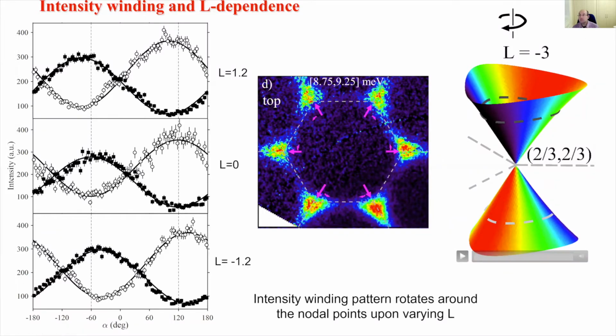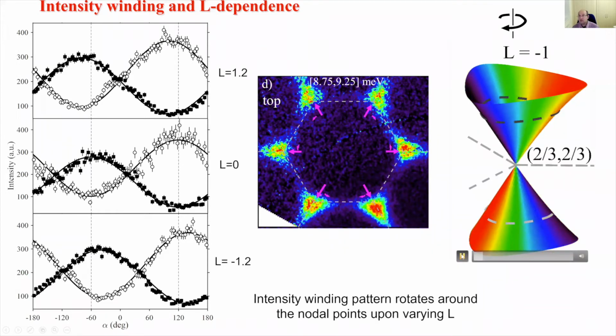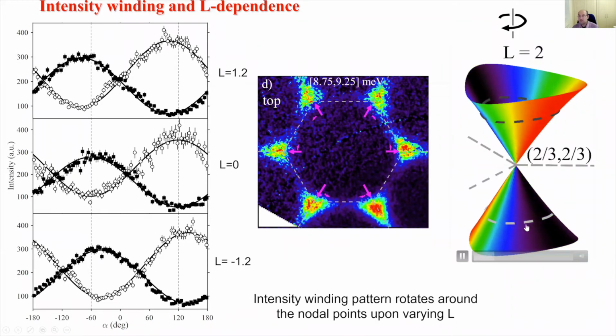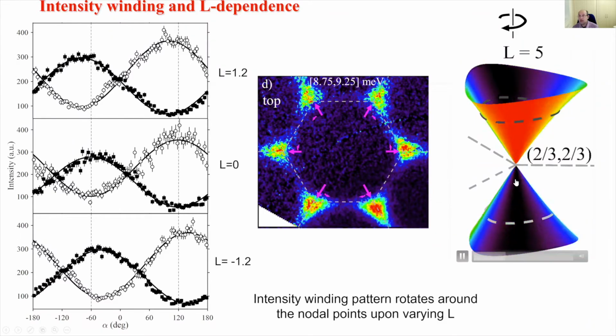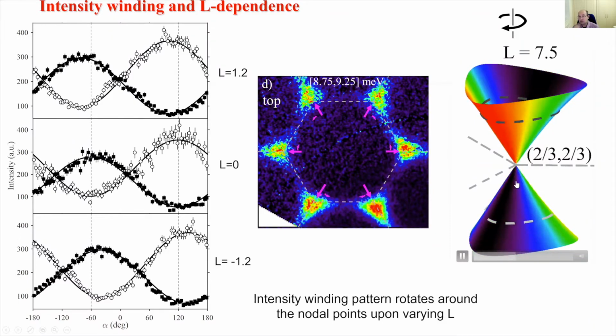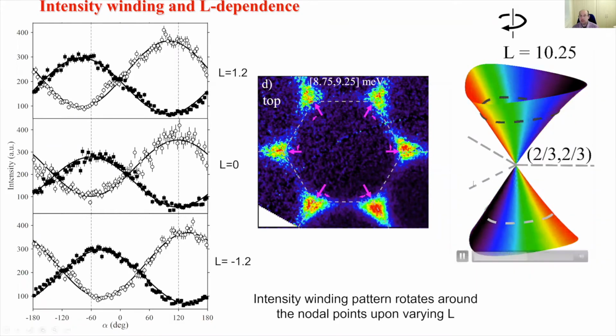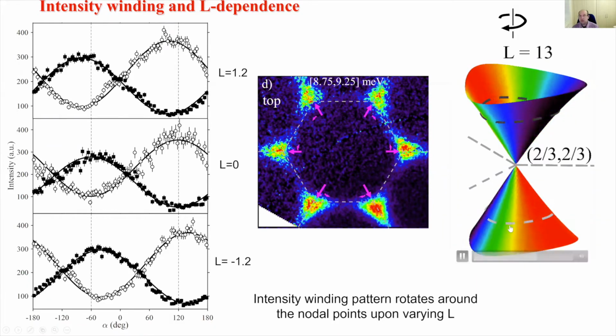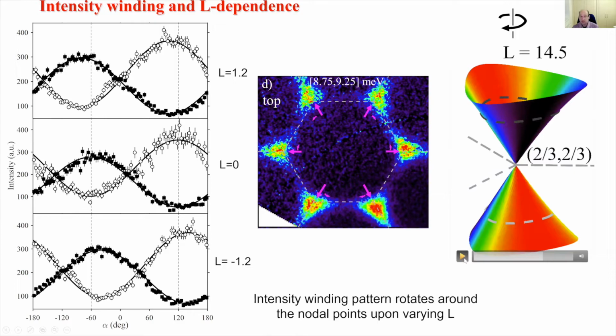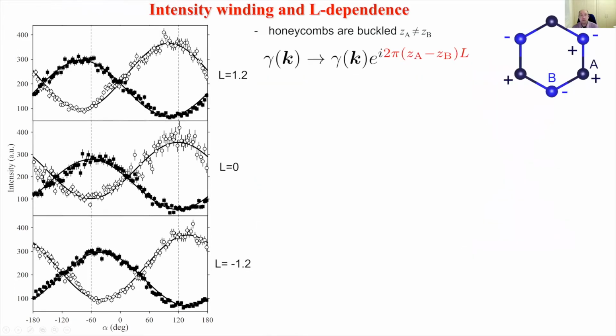So if we vary L, what's seen experimentally is that the region of strong intensity actually rotates round. So it's always in antiphase between top and bottom bands, but actually it rotates round as you move up along the L direction. So this puzzled us for a while, but actually it's very naturally explained if one considers the